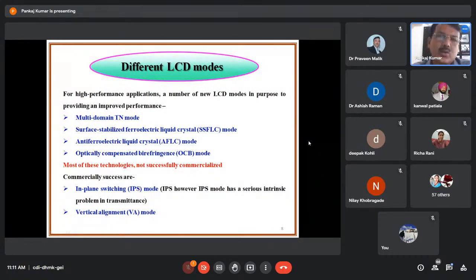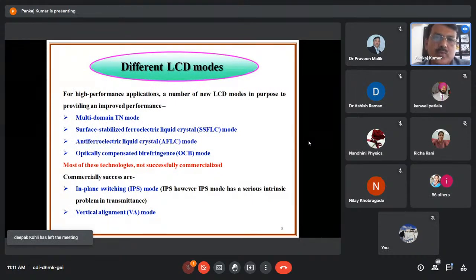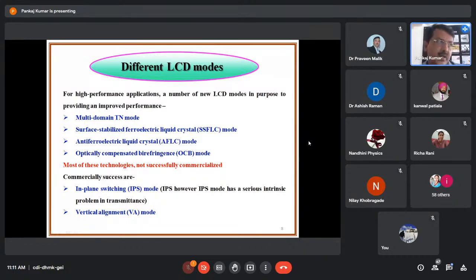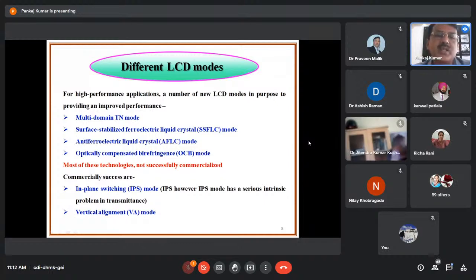For high performance applications, a number of new LCD modes providing improved performance are the multi-domain twisted nematic mode, surface stabilized ferroelectric liquid crystal mode, anti-ferroelectric liquid crystal mode, and the fourth one is the optically compensated birefringence mode. However, most of these technologies are not commercially successful. The commercially successful techniques are in-plane switching and vertical alignment. At present, in all the TVs and displays at your home, you will mostly find IPS or vertical alignment. Vertical alignment is the most prominent display because of some parameters. However, in-plane switching is also huge, and many companies are using in-plane switching also.